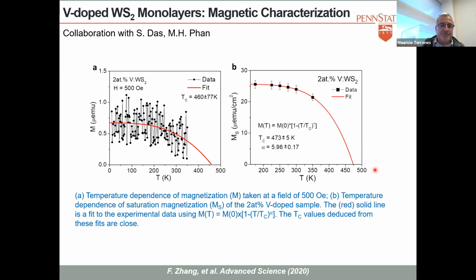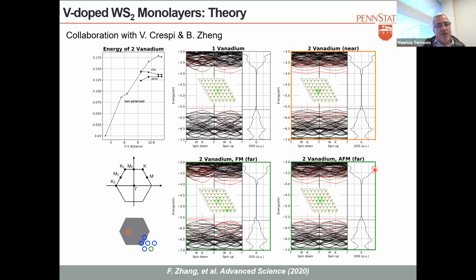That was tungsten disulfide. We have been collaborating with Vin Crespi's group doing the theory, and here one thing is clear. When you have just one single vanadium atom in the lattice, this is the spin density of states, and basically you can see a little bit of ferromagnetic signal. But when you have two vanadium atoms and they are far enough away, you can see again the ferromagnetic contributions happening here. And there are other configurations where you don't see ferromagnetism. So it depends how close or how far apart these vanadium atoms are.